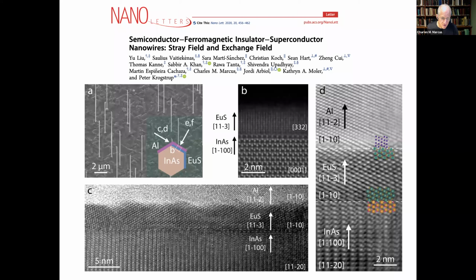What you see grown here is another transmission micrograph. This was what we saw before, the europium sulfide directly on the indium arsenide, and now the aluminum grown on top of the europium sulfide. The sequence of growth has to be that the aluminum goes on second, after the europium sulfide, because of the temperature of deposition. But nonetheless, two things to point out. One, the semiconductor ferromagnetic insulator interface is not only planar, but it's in atomic registry, as you can see from this picture.